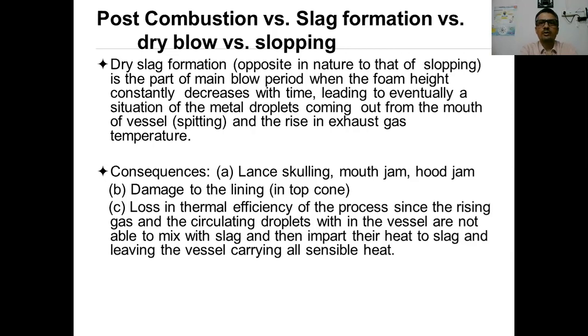In the main part of the blow, the foam height constantly decreases with time, leading to a situation where metal droplets come out of the vessel mouth, and this is also encountered along with a rise in the exhaust gas temperature. So whenever dry blow occurs, two things occur. The first is an increase in the exhaust gas temperature. Second is an increase in the volumetric flow rate of the waste gas also. The consequences are lance skulling, mouth jam, hood jam, damage to the lining, and loss in thermal efficiency of the process. Why? Because now the rising gases and the circulating droplets in the vessel are not able to mix with the slag and dissipate their energy to the slag, and they leave the vessel carrying all the sensible heat.